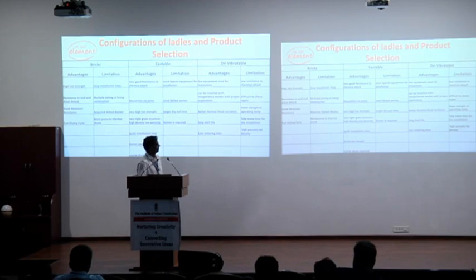But limitations are it needs special equipment like vibrating machines and mixer machines. We need to have skilled labor again to take care of the water additions. Dry out takes a longer time because you will be adding at least 4 to 6% of water to it, which has to be removed before introducing liquid metal, and the form is required.